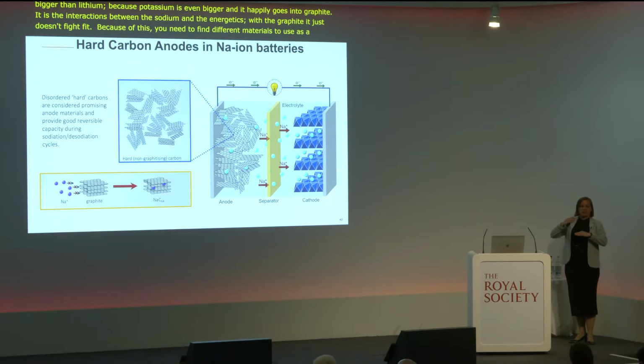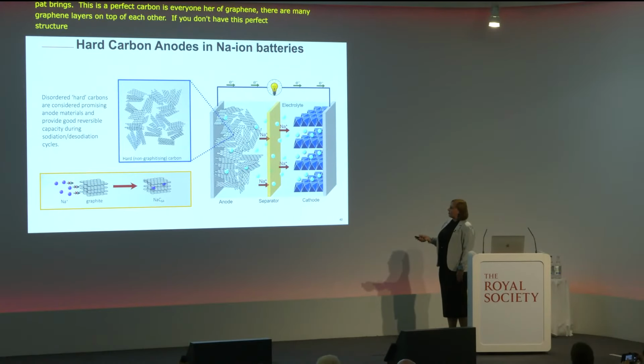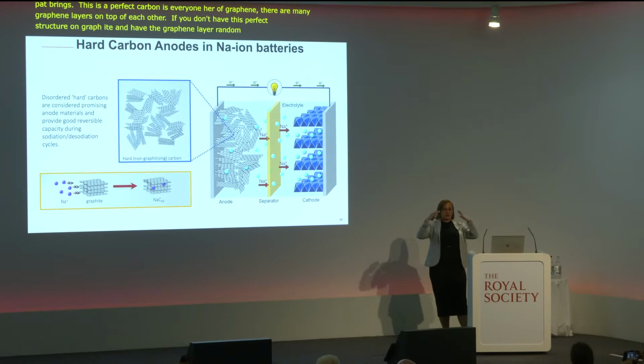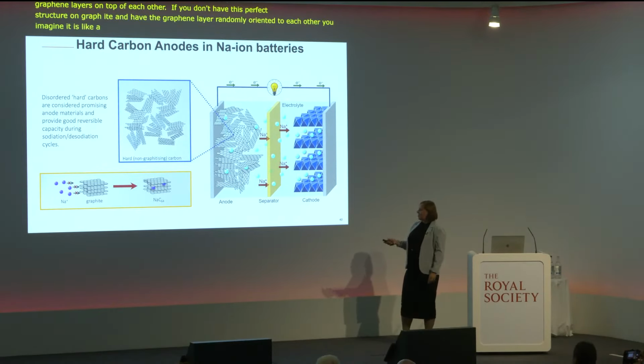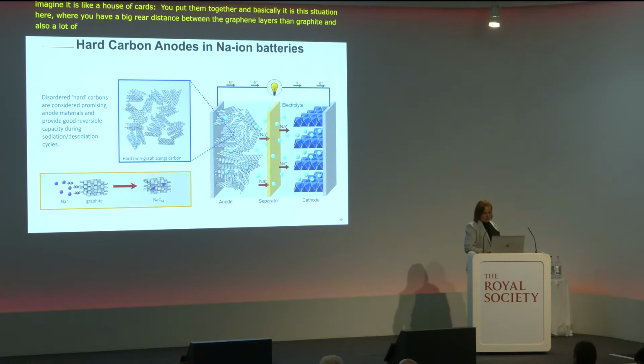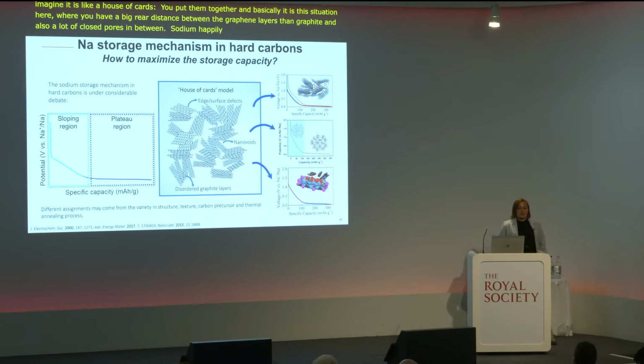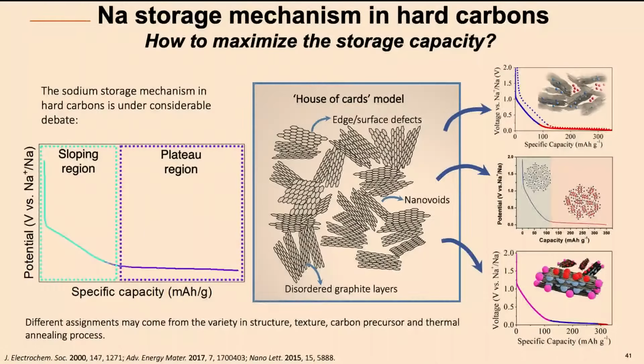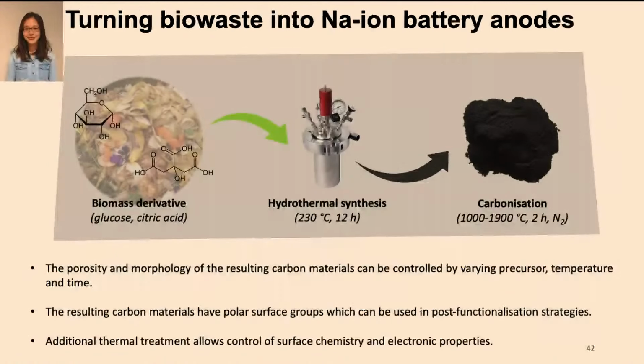Graphite is a perfect type of carbon allotrope where basically you have graphene. Everyone has heard of graphene. There's a big boom in the UK. So there are many graphene layers on top of each other. If you don't have this perfect structure, and you have these graphene layers randomly oriented with each other, you can imagine it like a house of cards that you put together. Then you have a bigger distance between these graphene layers than in graphite, and you also have a lot of closed pores in between. Now, sodium happily goes into this type of material. My group did quite a lot of research to really understand how we can maximize the amount of sodium that could go into such a disordered type of pseudographitic carbon, and we try to understand the mechanism of this.